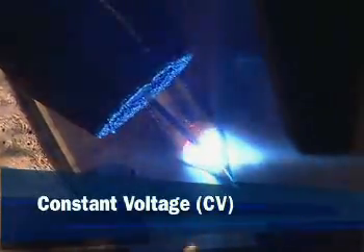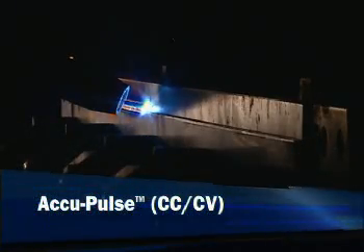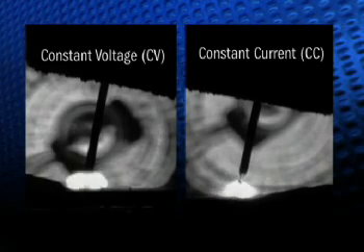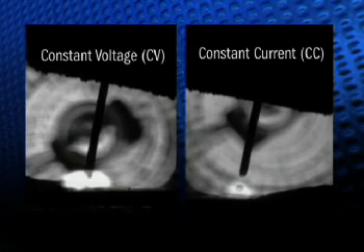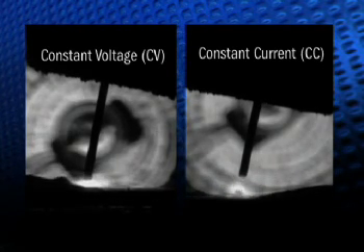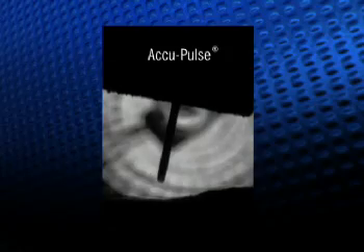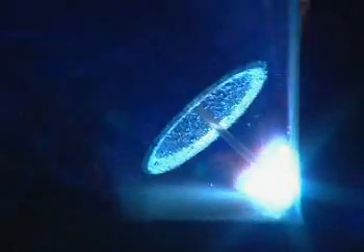CV welding typically allows short circuits in the arc. The shorter arc lengths attainable in CV meant faster travel speeds for manufacturing. AccuPulse and its variations allow the combination of spatter control and faster welding travel speeds by using both CC and CV in the same pulsed waveform. Once the target current is reached at the beginning of each pulse phase, the CC control turns off and the CV control loop turns on. The CV loop modulates the current to achieve the target voltage, allowing AccuPulse to create the desired wave shapes with arc characteristics that optimize desired arc performance. With the ability to better regulate pulsing parameters, AccuPulse allows operators to maintain a shorter arc length, regardless of stick out, with a more focused arc column. This results in greater speed and control.